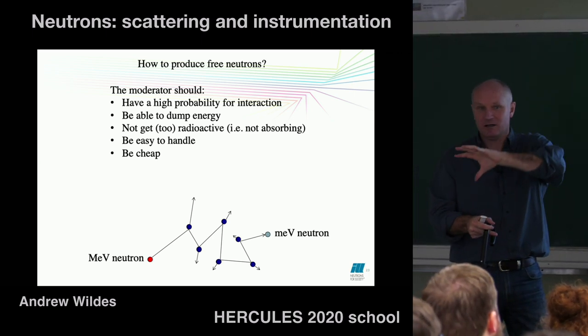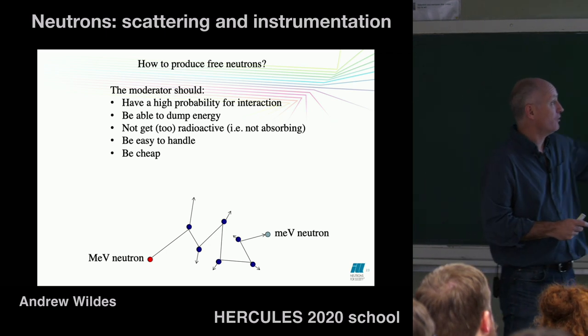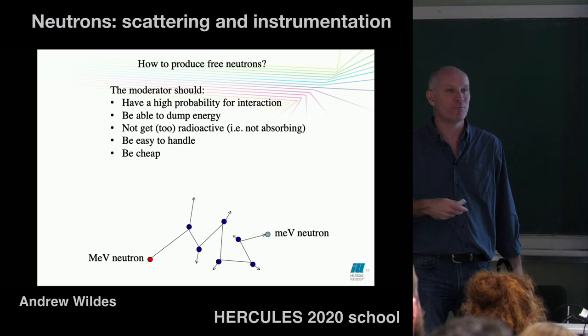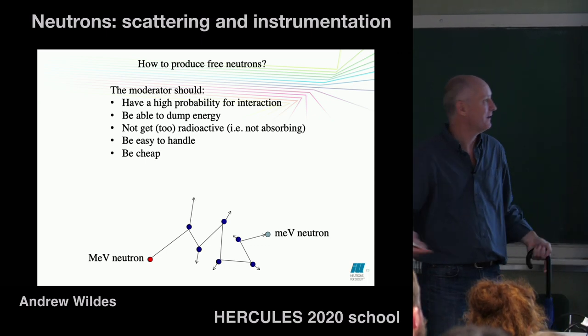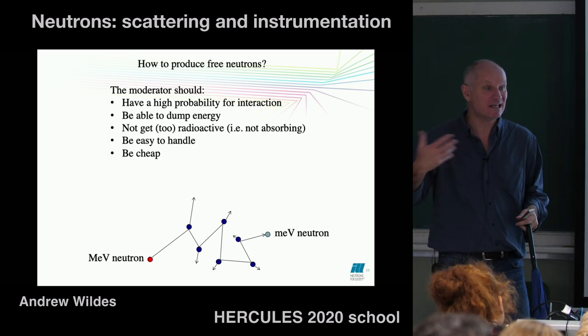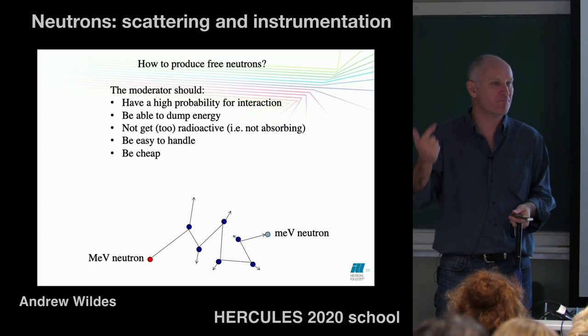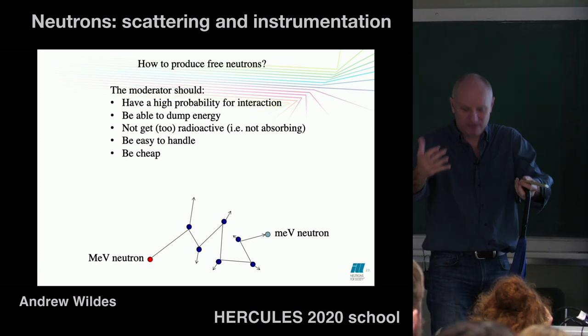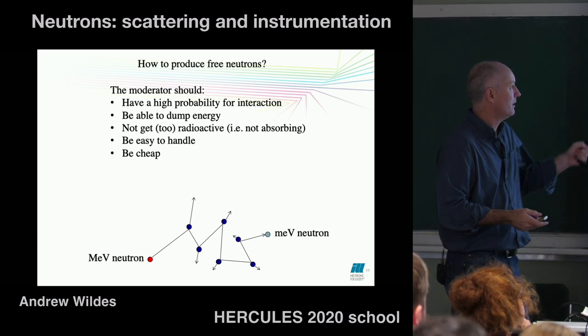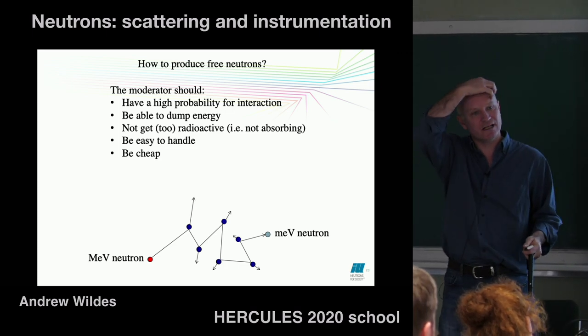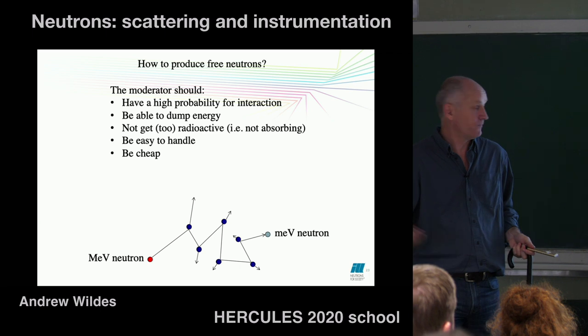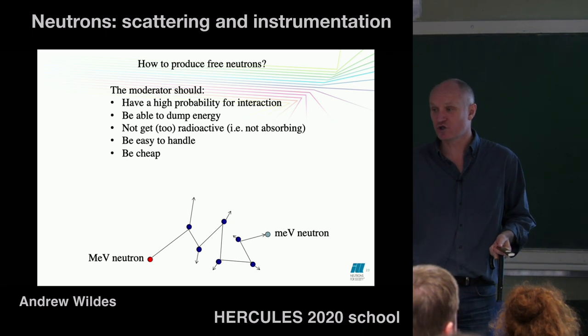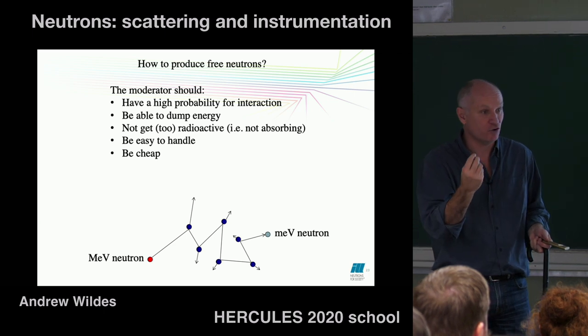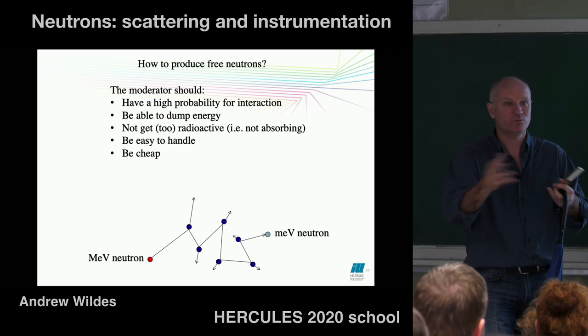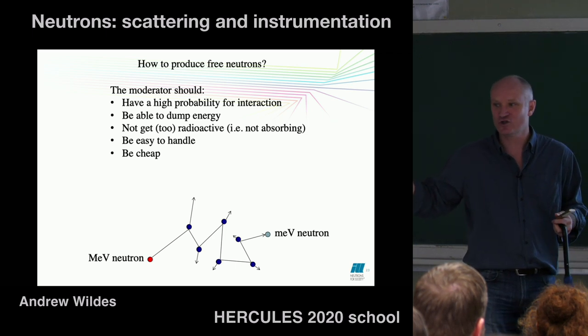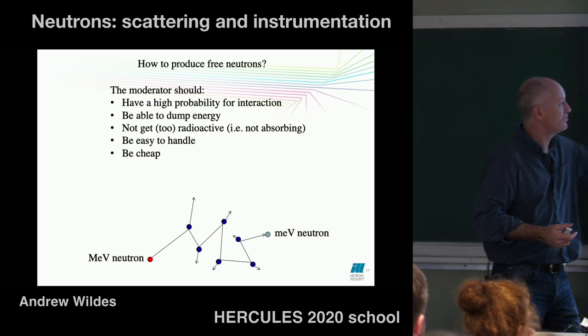So what do you use for this moderator? Well, there's a bunch of conditions that it should really satisfy. It's got to have a high probability for interaction. If it's got a low probability for interaction, then it's not going to work at all. You should be able to dump the energy. You're going to be heating it up. You don't want it to burn or melt or anything like that. It should be something that you can extract the heat out of relatively efficiently. You don't want it to get too radioactive. Radioactivity generally means that your material has absorbed a neutron, and then the nucleus that's absorbed the neutron becomes unstable and will decay. If it absorbs the neutron, you don't have the neutron to do scattering afterwards. So you don't want it to get too radioactive.